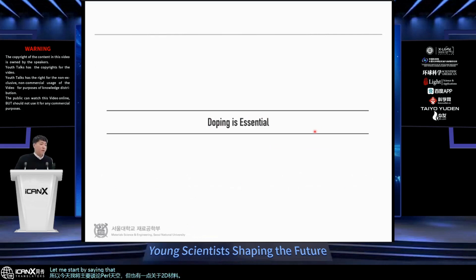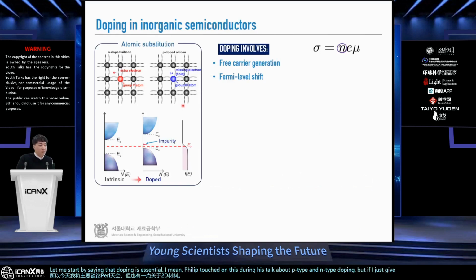Let me start by saying that doping is essential. Philip touched on this during his talk about p-type and n-type doping. I know this is not semiconductor physics 101, but it's always good to brush up on the idea of doping. For silicon, which is a group 4 atom, in a periodic lattice, you do an atomic substitution of silicon with a group 5 or group 3 atom to n-type dope and p-type dope respectively. Due to the heterovalent atoms introduced into the lattice, you're gaining or losing an electron, and therefore the result of this process is free carrier generation.